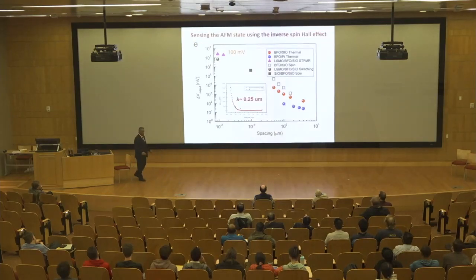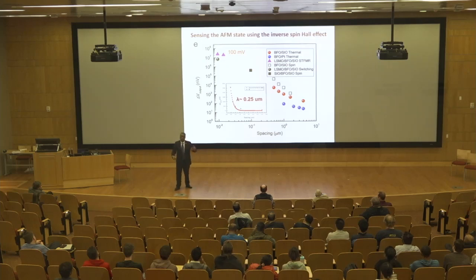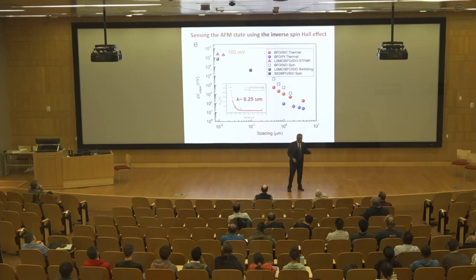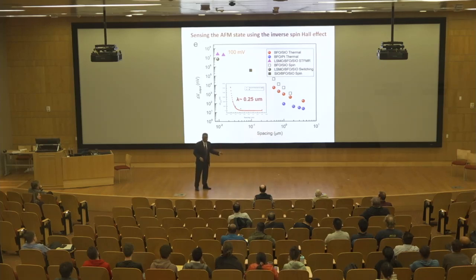What we then showed was, by going from 1 micron spacing, if I simply change the spacing from 1 micron down to about 10 nanometers, indeed, the output voltage goes up from nanovolts to about 10 millivolts. And if you remember, we started by talking about 100 millivolt as a required output voltage to start to think about real devices, and we're not too far off. We think there's a whole bunch of these kinds of materials. Materials like bismuth selenide, strontium iridate, other oxide materials which have very large spin-to-charge conversion efficiencies. So we are up to our eyeballs into looking at these kinds of materials.